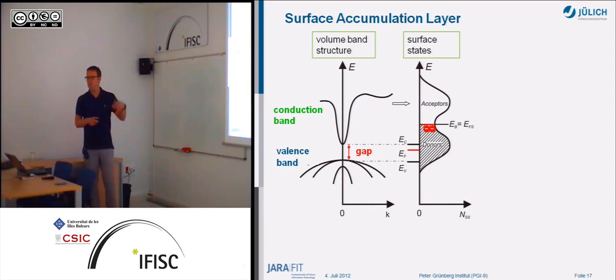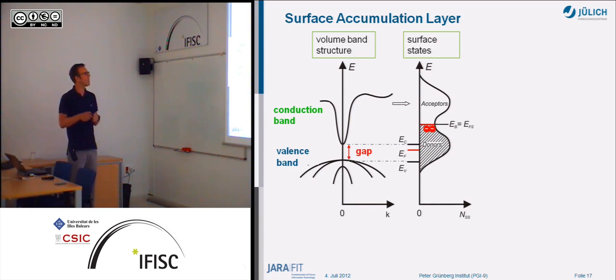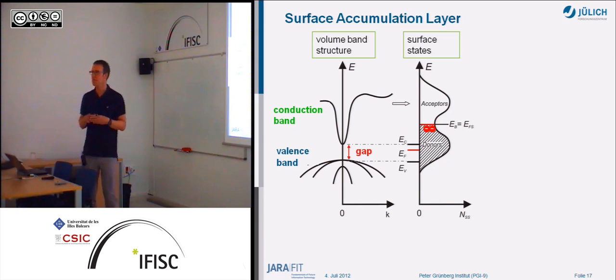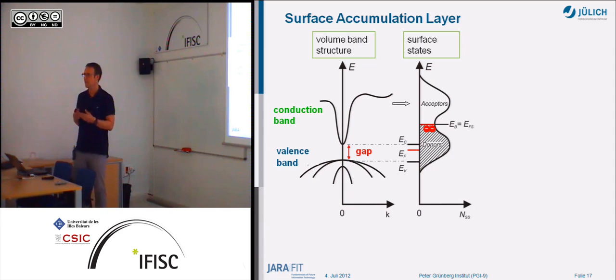So what determines the surface density of states is the average density of states you have here in your bulk semiconductor. And you see here you have a lot of states here, you have a lot of states here, but almost nothing here. And this determines how the surface states are distributed. And the fact is that because there's almost nothing here, the average point is here, and this is what determines the kind of Fermi level of the surface states here. So below that you have donor-like states, which are occupied usually if they are detached, and here you have acceptor-like states, and the Fermi level is around here. That's a charge neutrality level here.